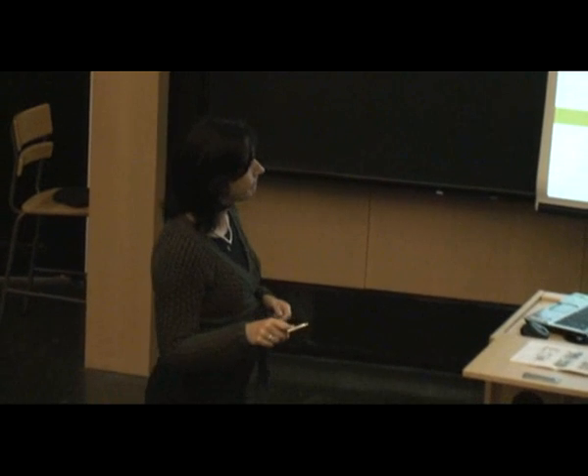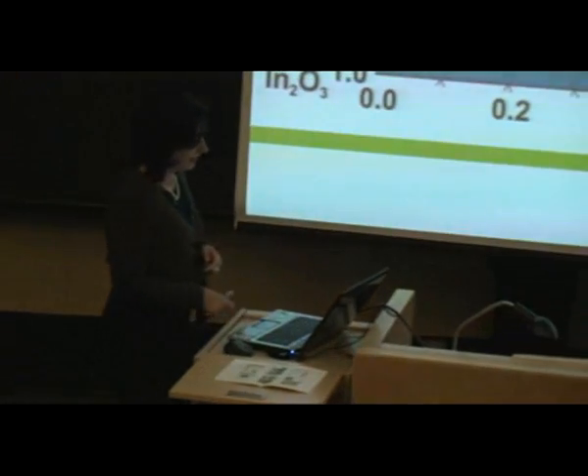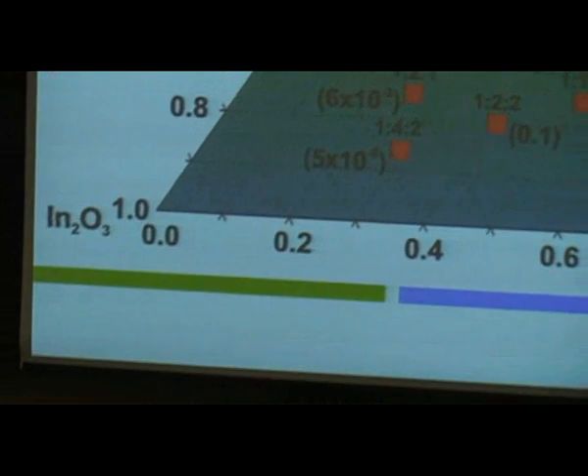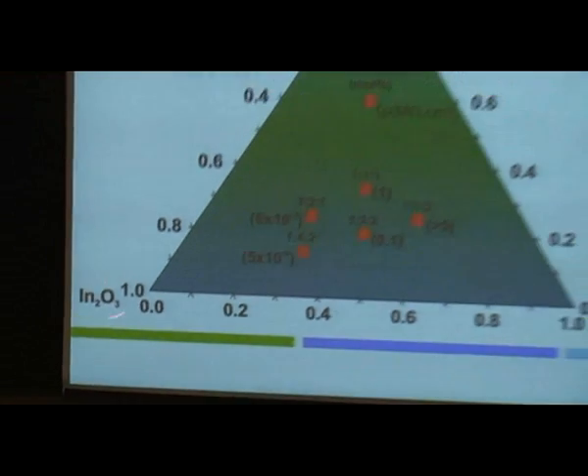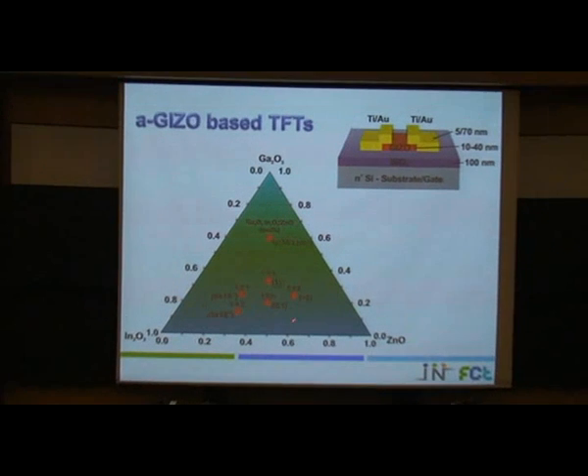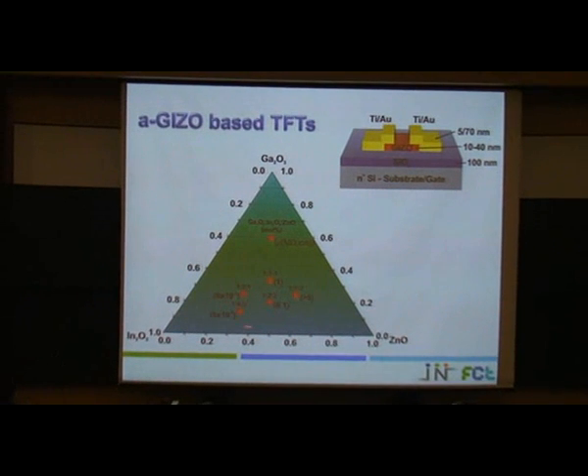But again, the material is amorphous. This is a typical diffractogram of a GIZO film, and the thickness here is much higher than the thickness used in the TFT. This is around 300 nanometers. This is a TEM image where we cannot detect crystals. And since we are using three oxides, gallium oxide, indium oxide, zinc oxide, it is more complicated to map all the possibilities and all the concentrations. And we are producing at this moment TFTs with these concentrations.